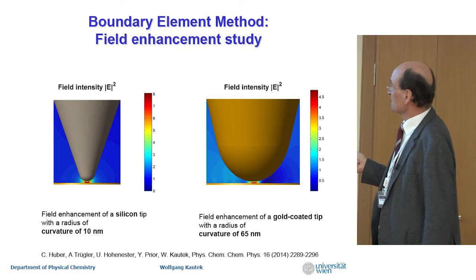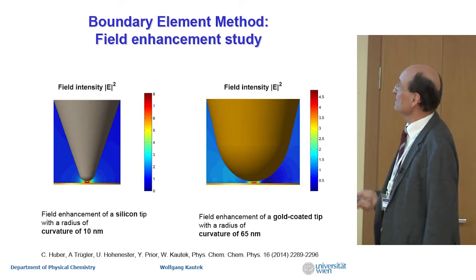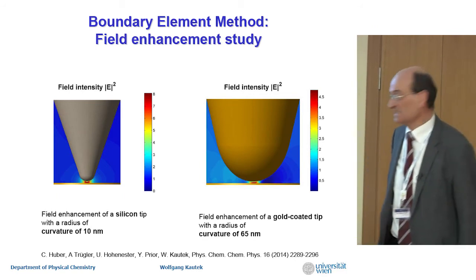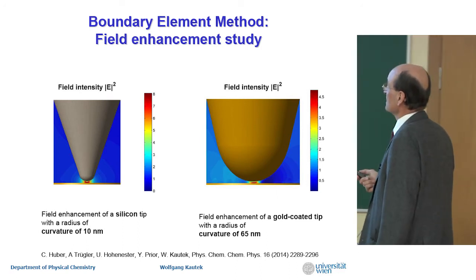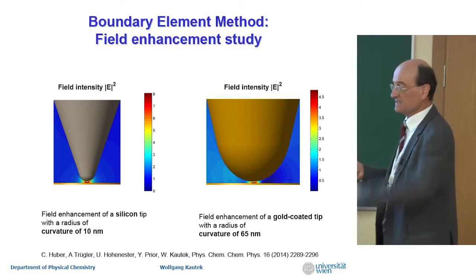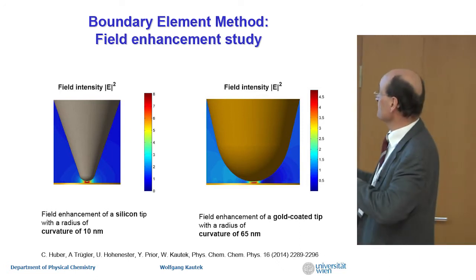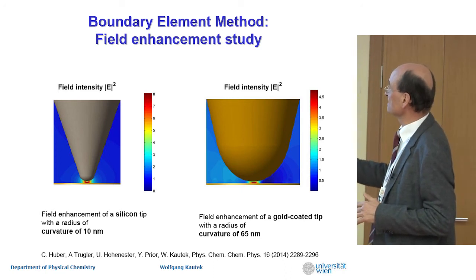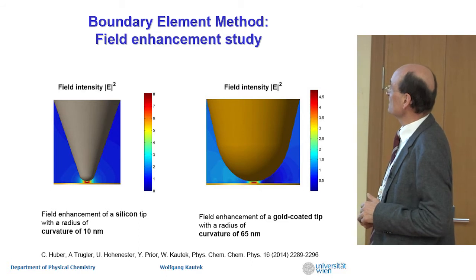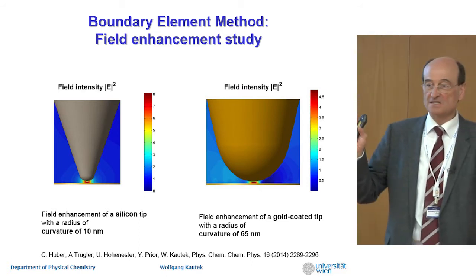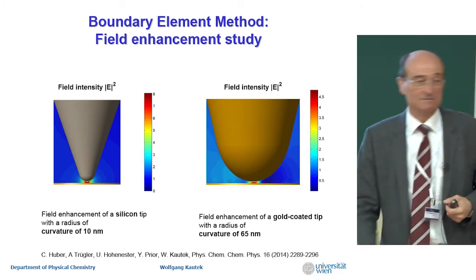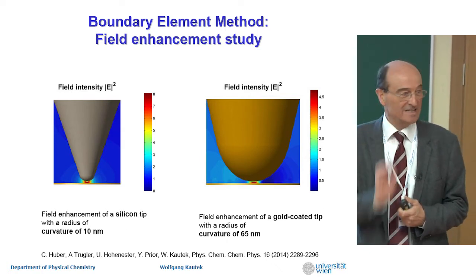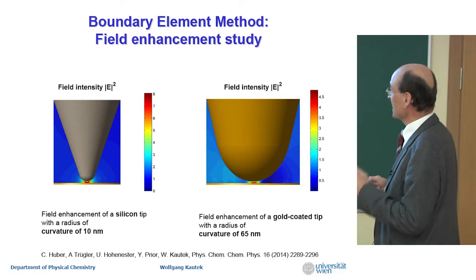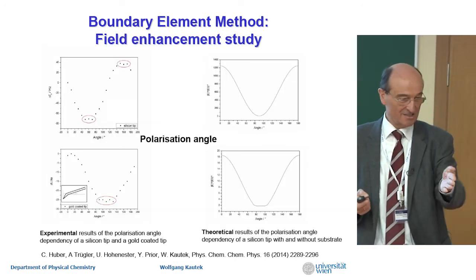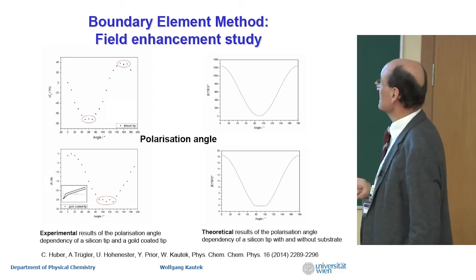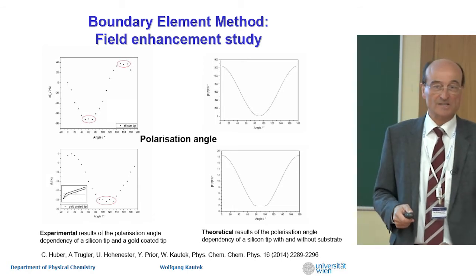And then we also calculated the density of the field at the tip by the boundary element method. Our colleagues in Graz did that, and I don't want to go into all the details, but it can be read. So we could calculate the field in presence of a substrate. This was not done before, with a gold-coated tip and a silicon tip with a curvature of 10 nanometers. Now what's very important in that business is, do you heat the surface and then scratch? Everybody can do that. Or is it a field which influences the substrate? And if that's the case, then of course, the polarization angle of excitation of the tip should have an influence. And we calculated that, and we could show experimentally, yes, there is an influence of the polarization.